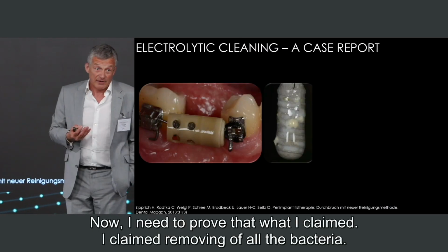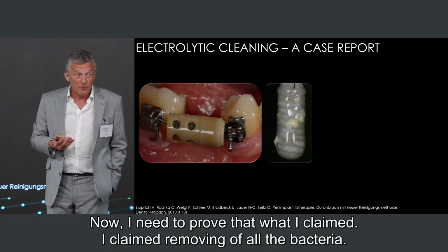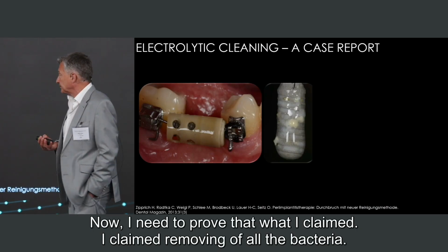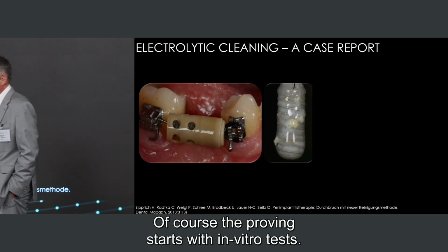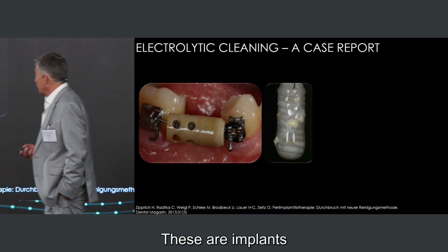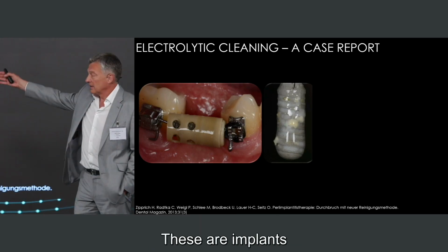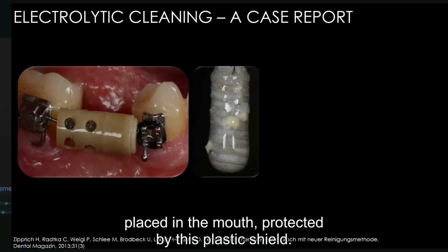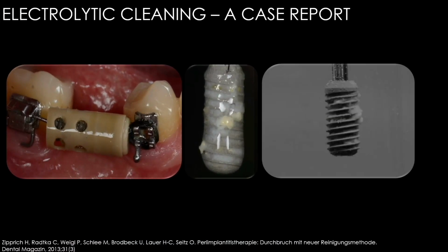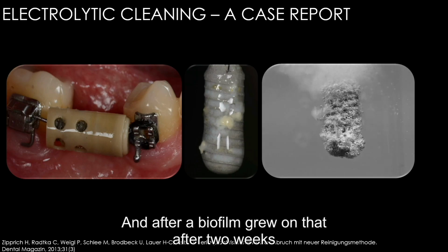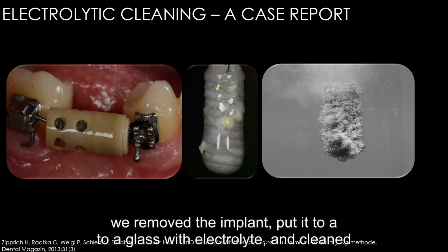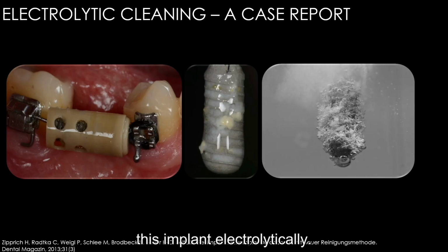In any case, as I will show you in a few seconds, now I need to prove what I claimed. I claimed removing of all the bacteria. Of course, proving starts with in vitro tests. These are implants placed in a mouth, protected by this plastic shield. And after a biofilm grew on that, after 2 weeks, we removed the implant, put it into a glass with electrolyte and cleaned this implant electrolytically.